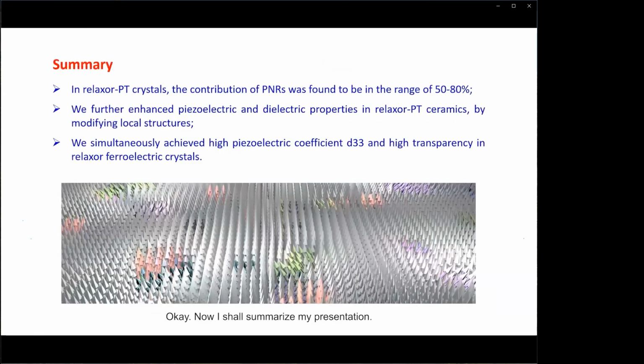Okay, now I shall summarize my presentation. Firstly, we clarified that in Relaxor-PT crystals, the presence of polar nanoregions is very important. The contribution of polar nanoregions to dielectric and piezoelectric responses is about 50 to 80% of the total response. This can explain why Relaxor-PT show much higher piezoelectricity compared to other MPB systems.